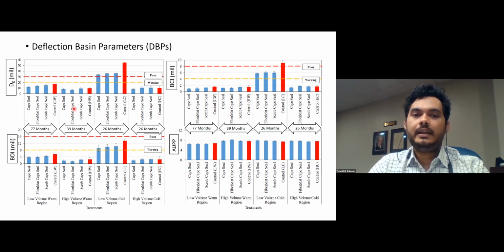The control sections are those sections that didn't receive any type of pretreatment or preservation treatment. Compared to the control sections, the cape seal treated sections have D0, BDI, and BCI values that tend to remain lower at the present time. For Lee Road, it has been 77 months of service. For US-280, 39 months of service. For CASA-8 and US-169, we found 26 months of service. So to this point, it is evident that the cape seal treated sections are performing better structurally.